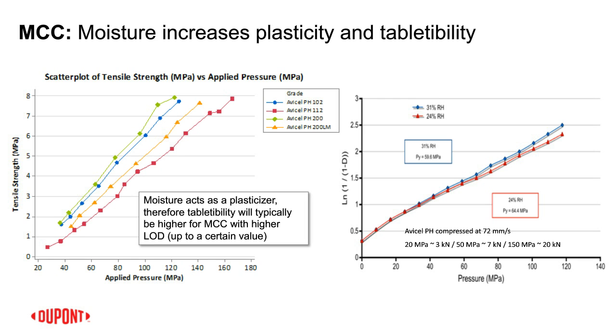So here on the graph on the left is a regular grade of MCC and its corresponding low moisture grade MCC. For example, Avicel PH 112 is a low moisture grade of Avicel PH 102, and Avicel PH 200 LM is a low moisture grade of Avicel PH 200. So everything else is equivalent. The only difference is moisture content. And you can see the lower moisture grade has a slightly lower compactibility than the regular grades.